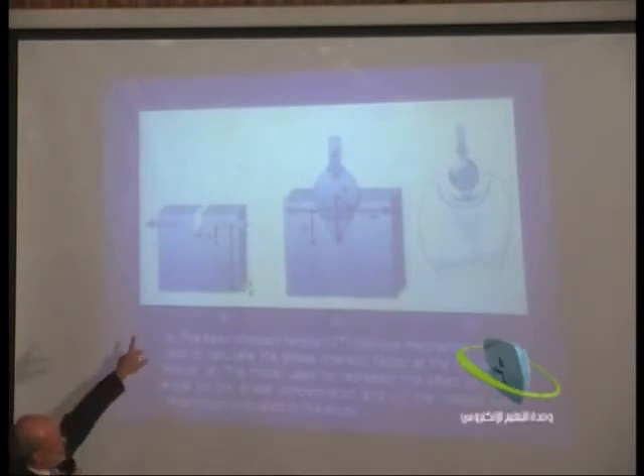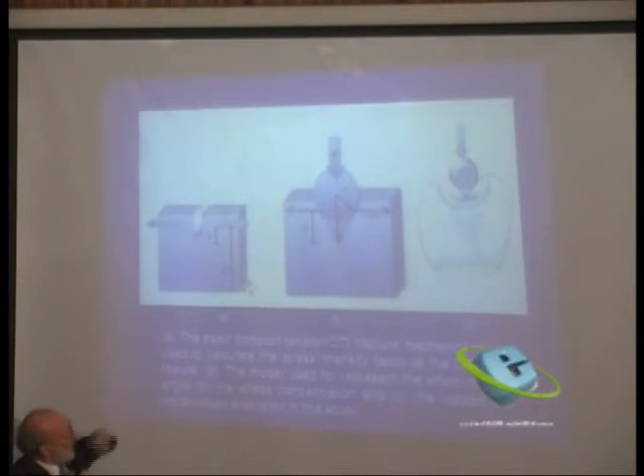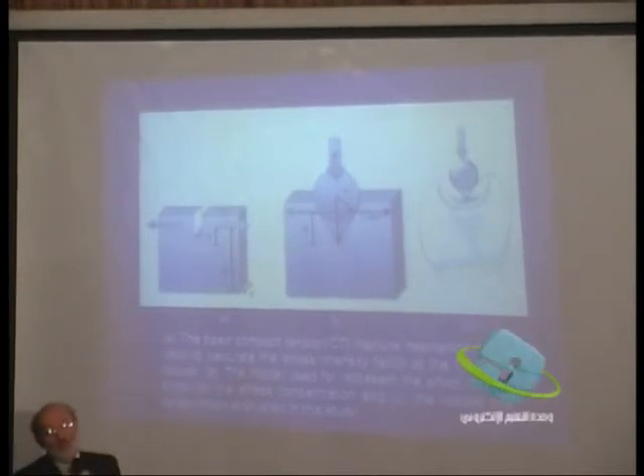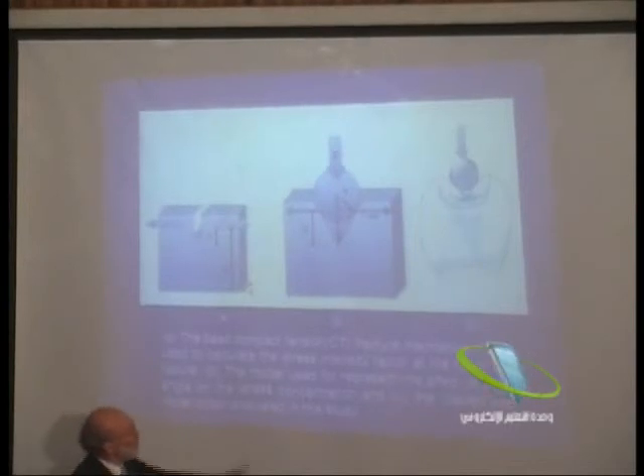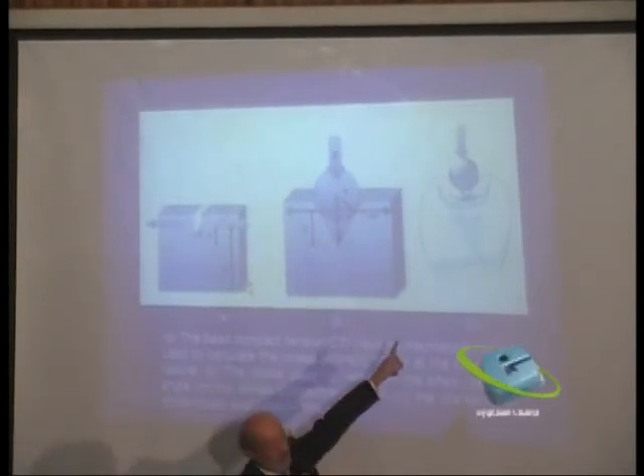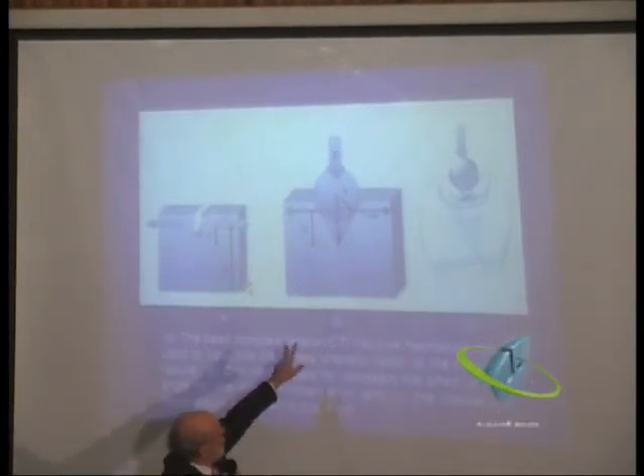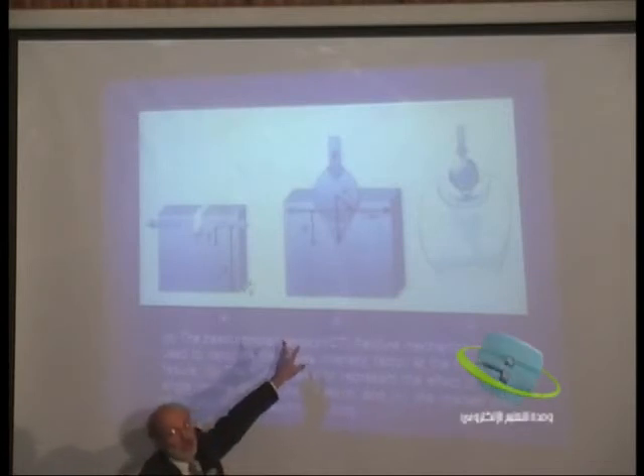Now, my background is in materials and physics and mechanics, and so one of the ways that we do fracture tests in metals and many other systems is what we call a compact tension test. And that's this test here. And then I felt that, well, this is not too remote from the crown system that we use. So here is the crown, and here is how it was loaded. So we could then reinterpret that in terms of this test here.